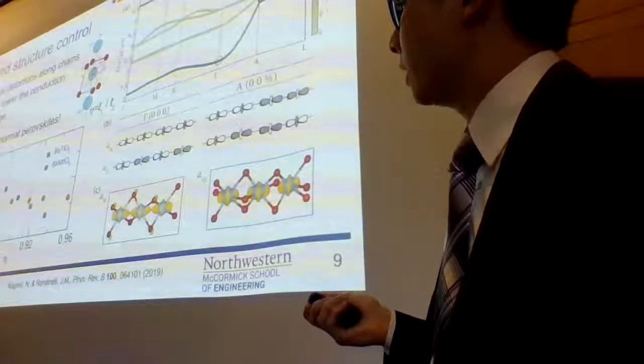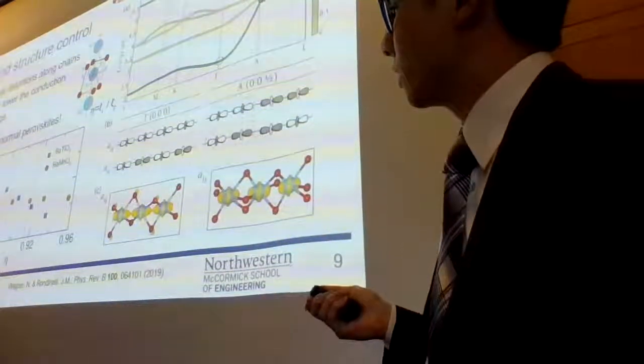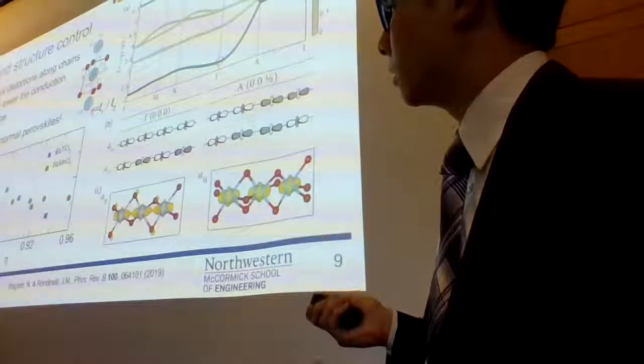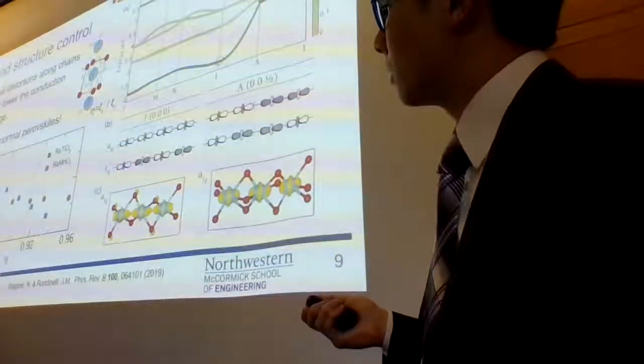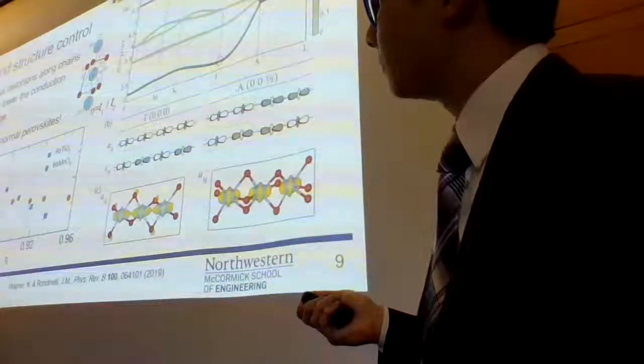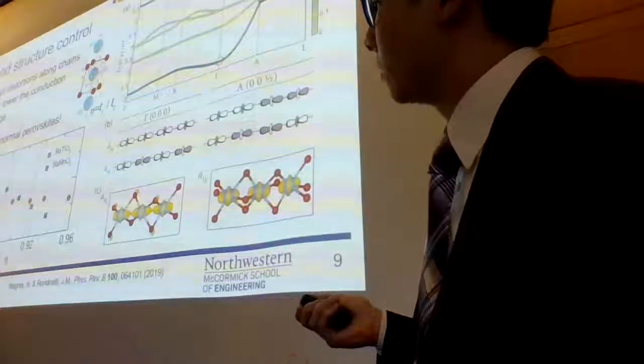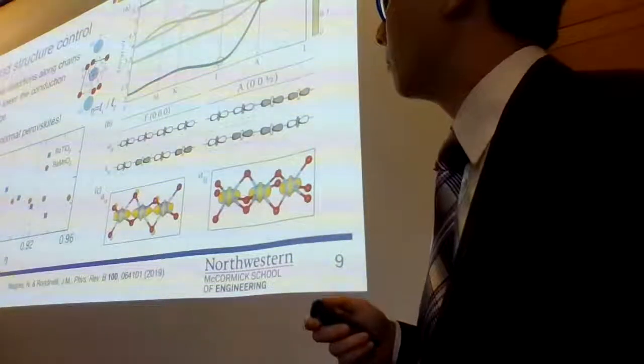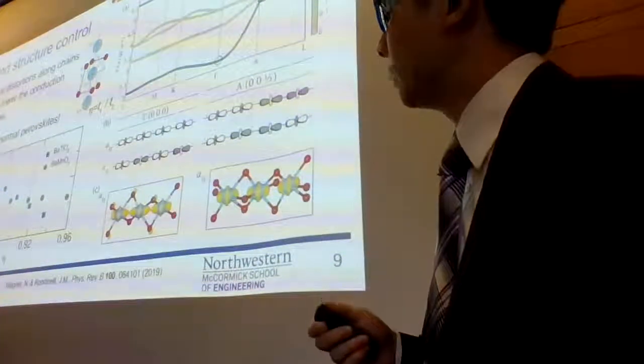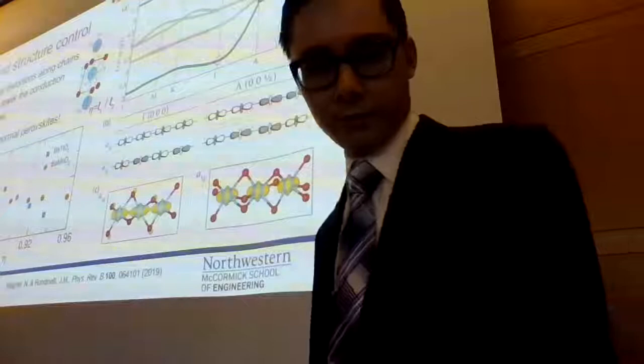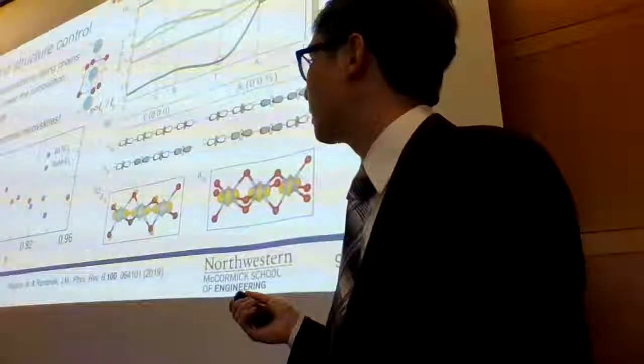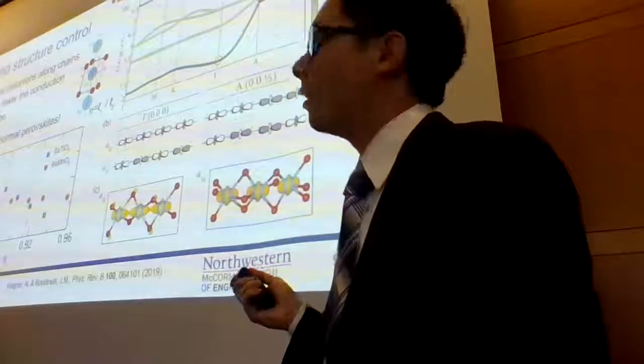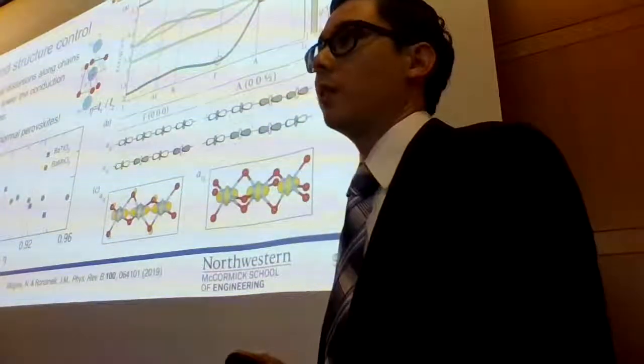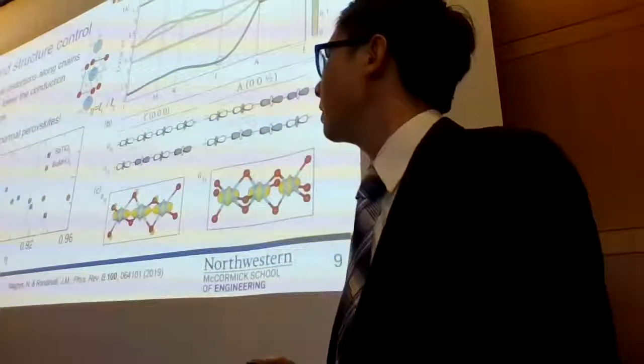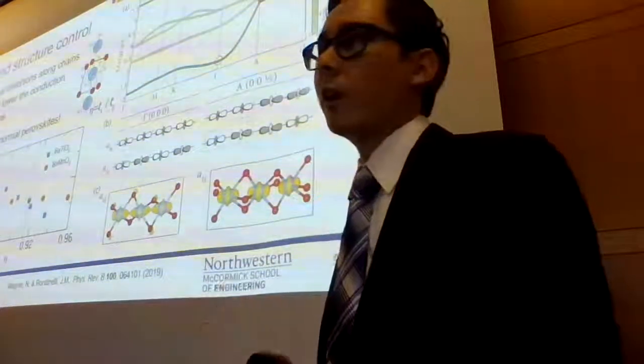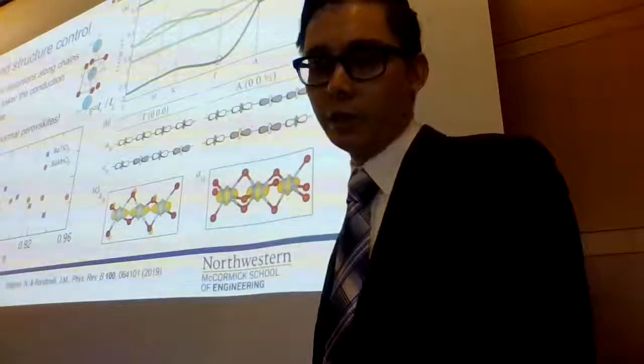But here for barium titanate, you can see these dashed lines represent the zero strain, or unstrained, case. As you go between these neighboring eta values, you're changing the band gap by almost on the order of half an eV, which is quite sizable. And I should mention again that there is an analog in rhombohedral perovskites, which are a known low temperature phase of, say, barium titanate, but the effect is much weaker there, and it's more difficult to control that distortion there.